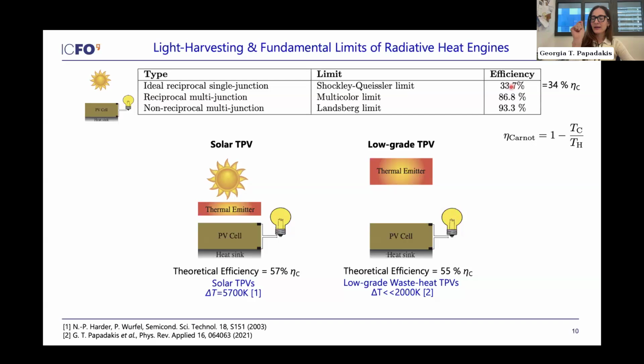And instead of showing exact numbers of efficiency, I normalize all the efficiencies to the Carnot limit. So I take the temperature of the sun, which is 6,000 Kelvin. I take the temperature of the cell, which is 300 Kelvin. So 33.7% actually corresponds to 34% of the ultimate Carnot thermodynamic limit for these temperatures. Now, as I already said, if I take a solar TPV and I put a thermal emitter in between, and I make the emission coming out of this thermal emitter that is heated by the sun very narrow band, you'll see that I get a much higher thermodynamic efficiency.